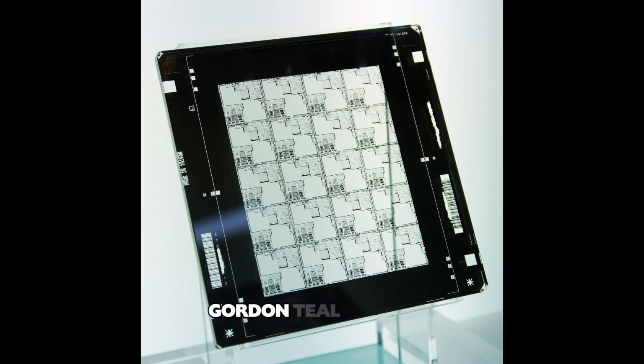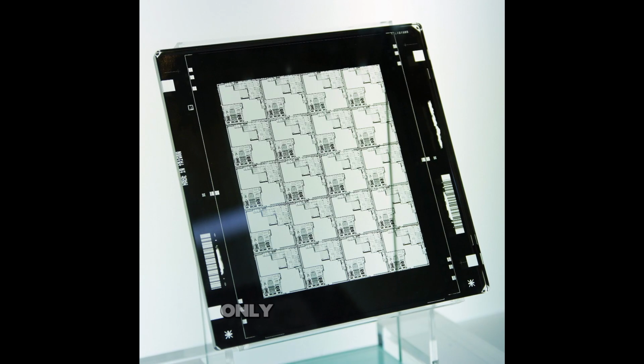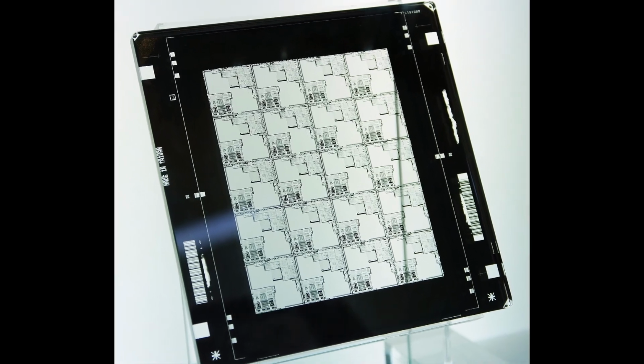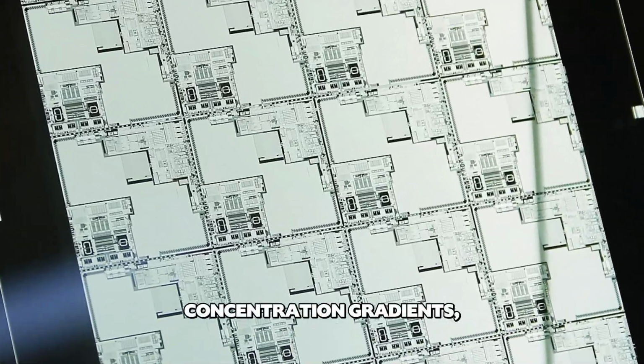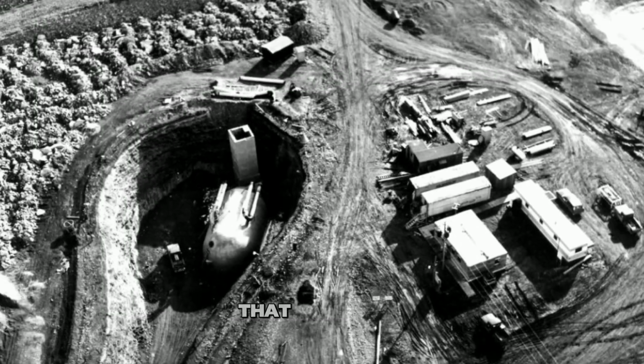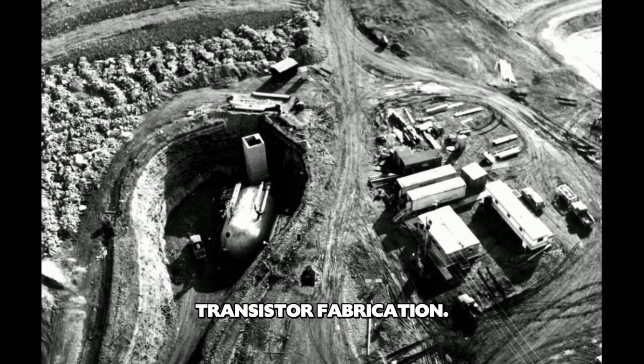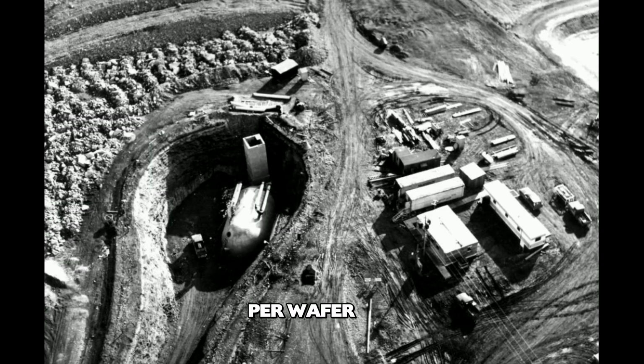Gordon Teal at Texas Instruments was growing silicon crystals, using a process where he pulled the crystal from the melt while introducing controlled amounts of dopant gases. The technique worked, but yields were terrible. He'd produce a silicon ingot 6 inches long, slice it into 30 wafers, and discover that only 3 or 4 had uniform doping. The rest would have concentration gradients, crystal defects, or contamination that made them unsuitable for transistor fabrication. At $10 per wafer for materials and labor, every failure was expensive.